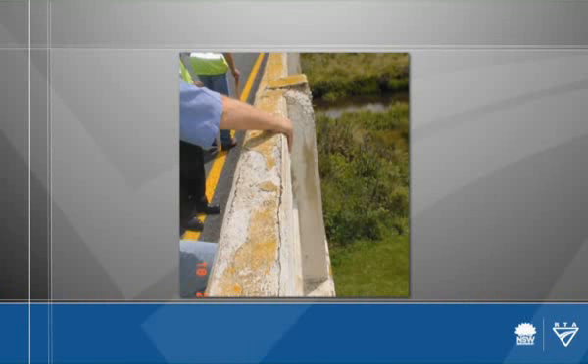Now if you look at this photograph here, Peter, you can see that there's a deterioration of that concrete rail, and this bridge is in a freeze-thaw situation. So what happens is if the concrete is designed with an air entraining agent, the air entraining agent produces discrete bubbles of air through the concrete, and so you end up with very small pores, but it's very impermeable to water. So in freeze-thaw conditions, the water won't penetrate into the concrete, because if it does, when it freezes, it expands and will blow the concrete apart. So an air entraining agent in cold climates is a very important admixture.